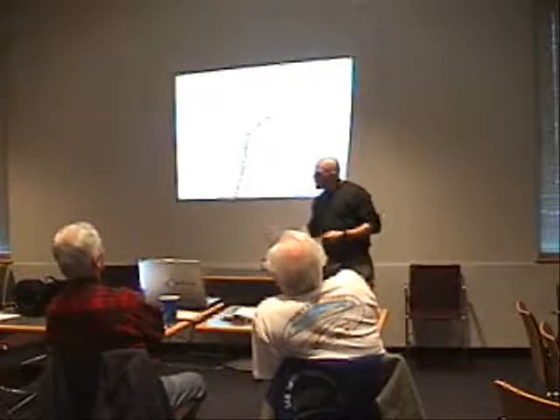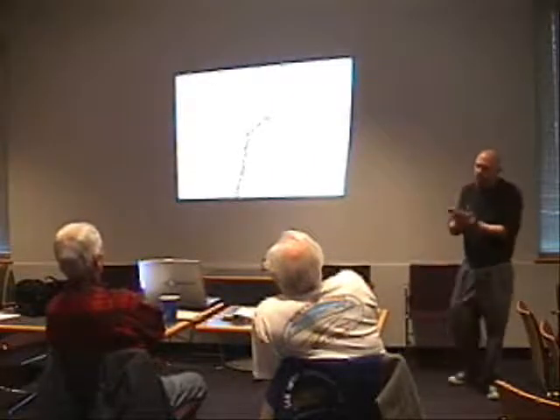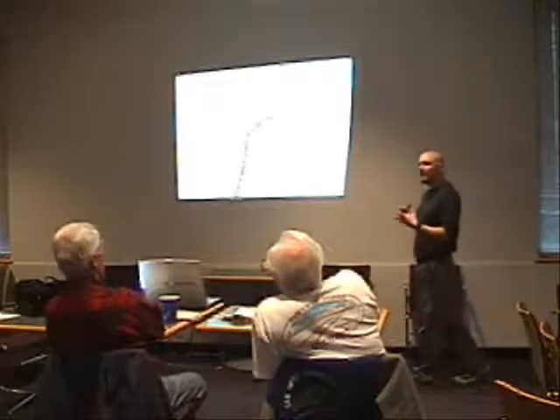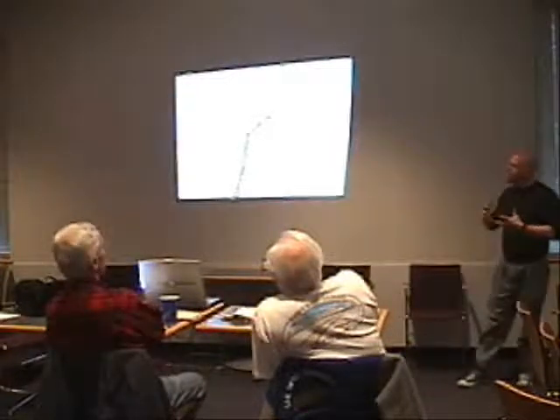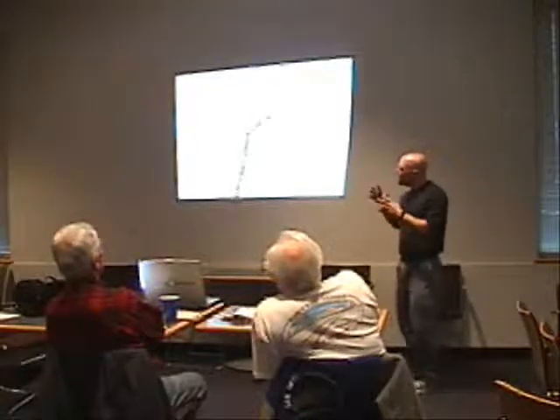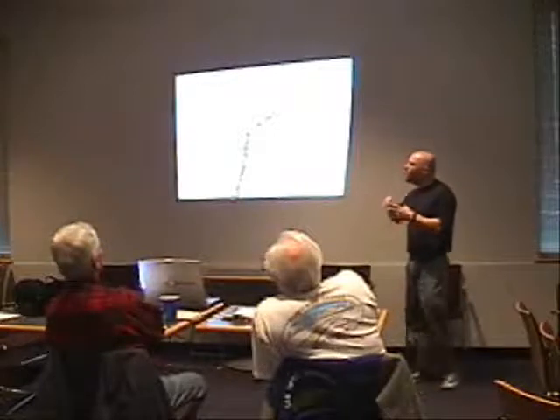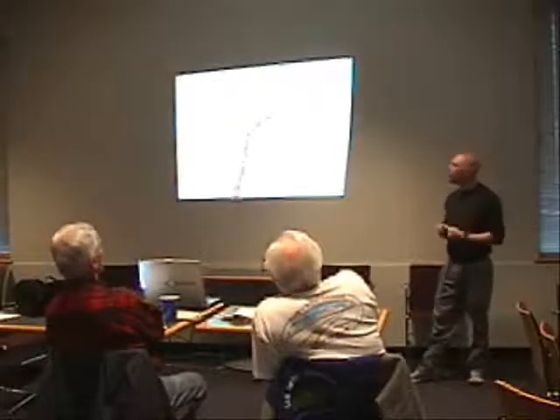The stainlesses will have two little bars here, either the active or the passive state. If it's got an oxide built up on the surface, it has one sort of galvanic reactivity. And if it doesn't have one, it has another, which means that they're also susceptible to galvanic corrosion due to wear on the surface. And so you actually see a lot of erosion corrosion and cavitation corrosion with stainless steels in aggressive environments because that passive film breaks down and it galvanically attacks itself.